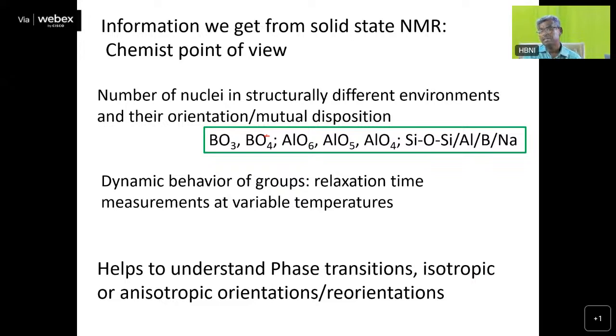Similarly in the case of silicates, we have silicon, oxygen, silicon, then again oxygen and then again silicon. If you take the first silicon, then the near neighbor is oxygen, the second neighbor is silicon, the third neighbor is again oxygen, and the fourth neighbor can be aluminium or boron or sodium or potassium or any other ion. But solid state NMR is sensitive to changes even at the second and third near neighbors. So this makes solid state NMR a versatile technique for understanding the structure of borosilicates, boroaluminates, aluminosilicates, etc.